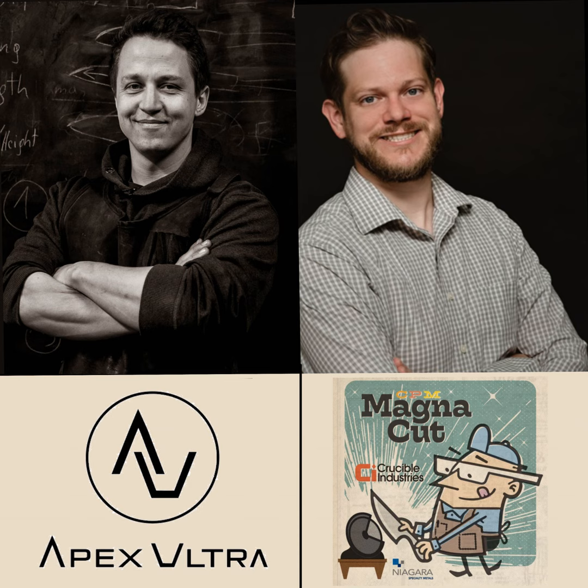But is the final hardness going to be as high as with oil then? Copper is actually a really strong conductor, so I'm going to say it's achievable. With thin blades and 2 copper pieces, everything clean, I say you achieve full hardness with Apex Ultra. We should point out that sometimes you can get full hardness or near full hardness, but there can be pearlite that forms, so carbides that form during the cooling if it's not fast enough, and that will reduce your performance.